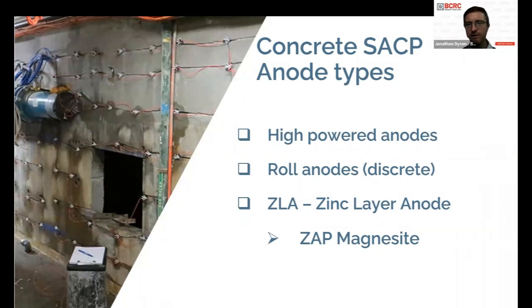As I said before, there are some higher powered anodes available in the market now, which can provide true cathodic protection. I'm talking about sacrificial anodes. And then there's also other sacrificial systems like roll anodes, discrete anodes which can be drilled into the structure, and then the anode material will consume preferentially to the steel rather than the steel corroding.